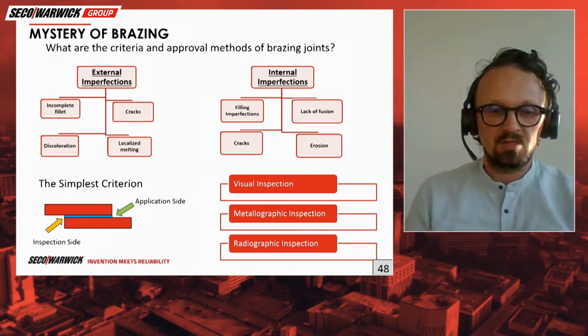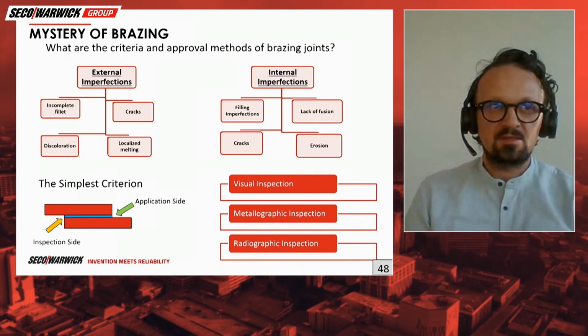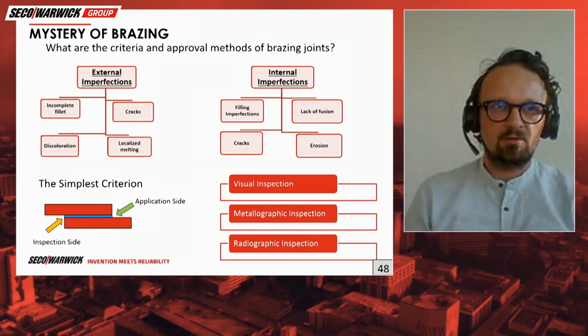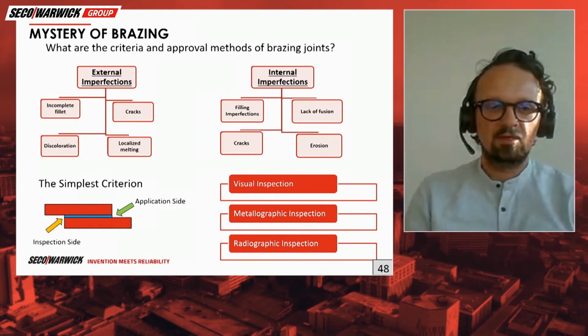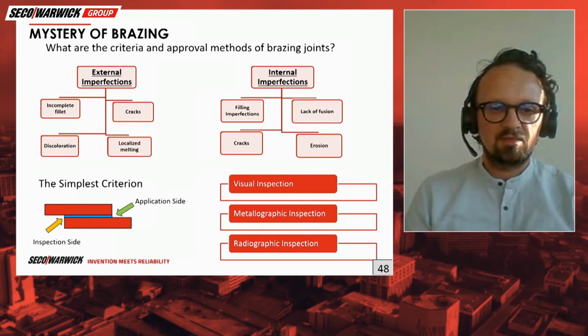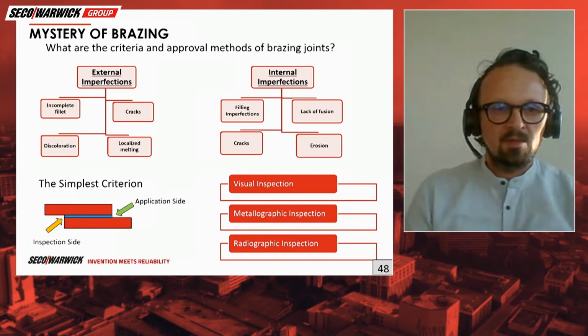In erosion, you might see some erosion that is not a big deal, or sometimes erosion/diffusion is used as a joining technique, where we heat up so long that we erode the base material so that it mixes with the braze alloy, creating a very strong joint. But that's different. We could say that's diffusion brazing.